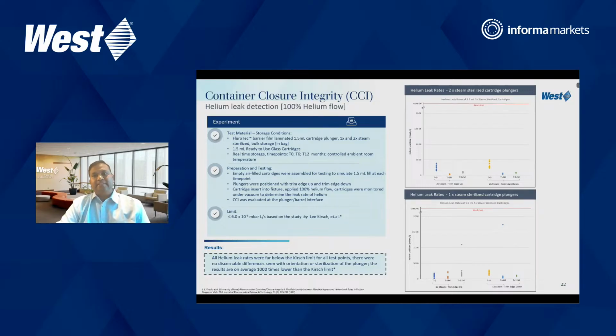Similarly, the next important aspect is CCI, the container closure integrity. Here we have done CCI by using helium leak detection, which is a quantitative test, again with 1x and 2x steam sterilization. The study is up to 12 months at controlled room temperature, and the limit according to Kirsch is 6 into 10 to the power minus 6 millibar. But when you see on the right side, whether it is 1x or 2x steam sterilized, the results are around 1000 times lower than the actual limit specification set by Kirsch. This is what we observed at time 0, 6 and 12 months, where the actual results are way lower than the specifications. That gives the confidence that whether it is trim edge up or down with 1x or 2x steam sterilization, we have consistent break loose and glide force, passing CCI by using the helium leak test.